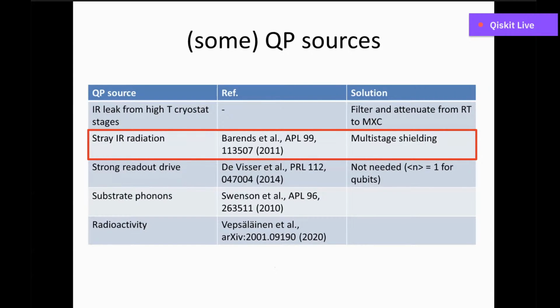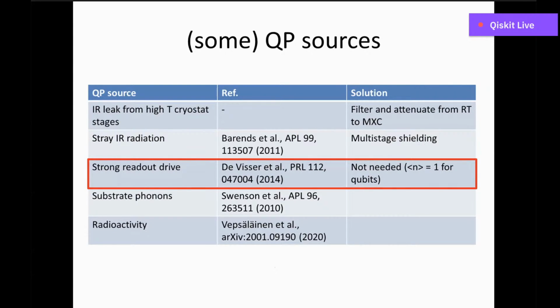Another source is infrared radiation coming from outside, as was first pointed out by Barends and co-workers. This is fought by multi-stage shielding and by using absorbing coating for the shielding. And also, we take care of that. Another possible source is a strong readout drive, the tone with which I excite the resonator itself, as was pointed out by De Visser and co-workers, which is relevant for the detector community, but not for the superconducting qubit community, because the readout power is of the order of one photon circulating in the resonator, which is not enough to break Cooper pairs.